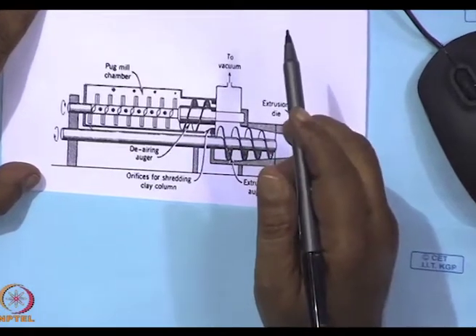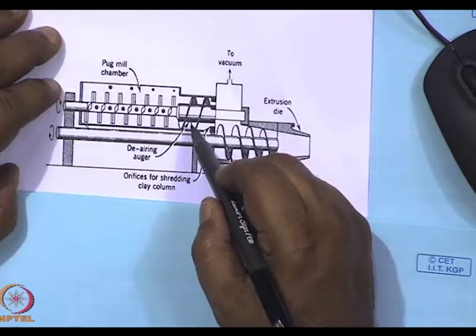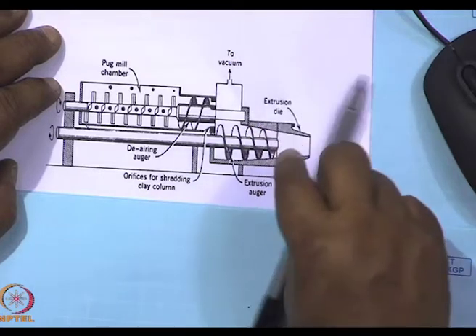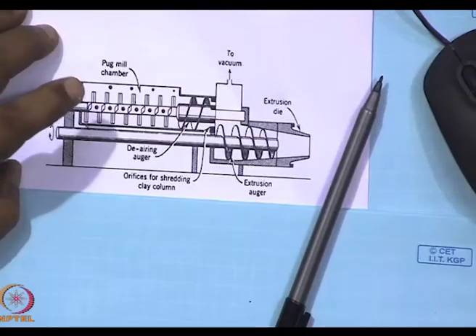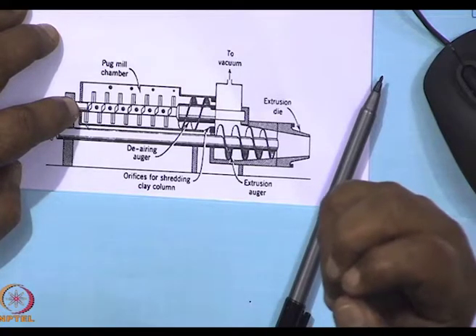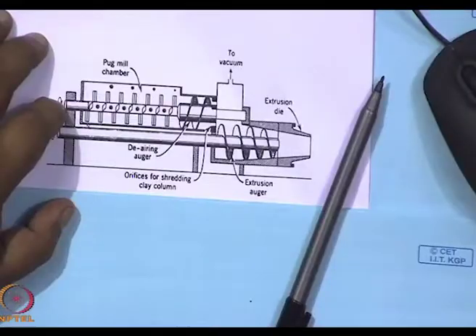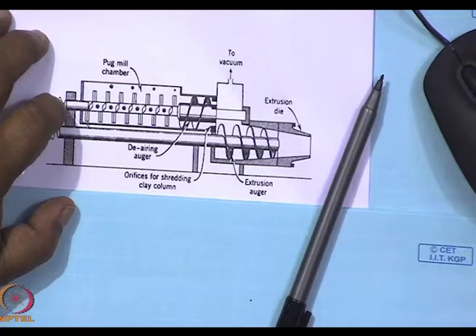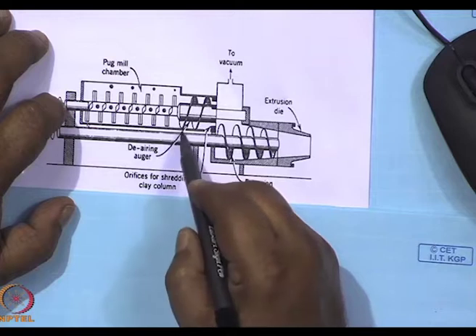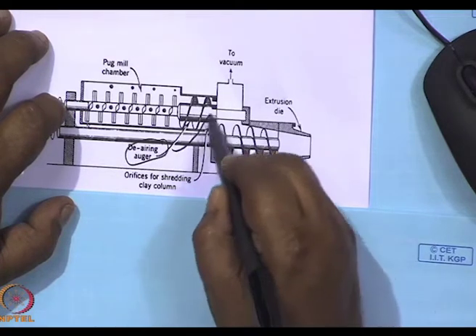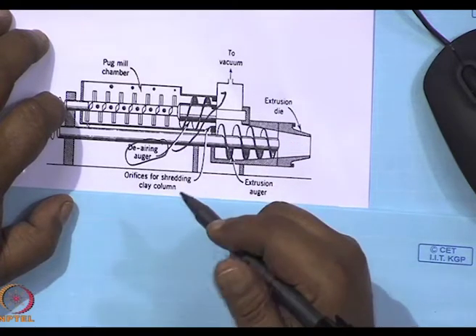Here is the pug mill chamber. Here is where de-airing occurs. Why? Because whenever, let's assume you have taken a bucket of water and you are rolling your finger in it, you will see bubbles in it. So when in this pug mill chamber, the ceramic particles and the polymers are being mixed, especially if there is a counterclock motion shaft, there will be a very large amount of bubbles which are being generated. So in this particular case, we have a de-airing hose which is connected to a vacuum pump, so that the air bubbles are removed from the polymer ceramic mix before it is extruded.